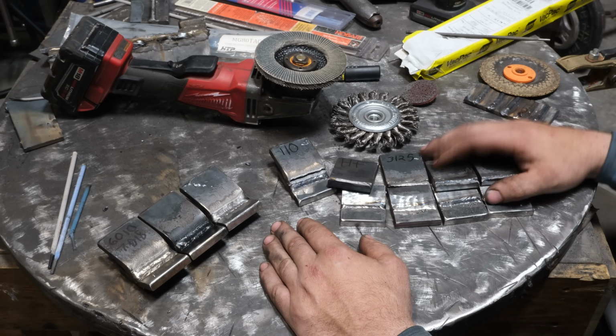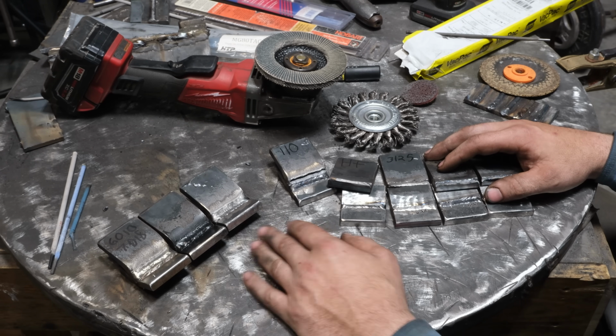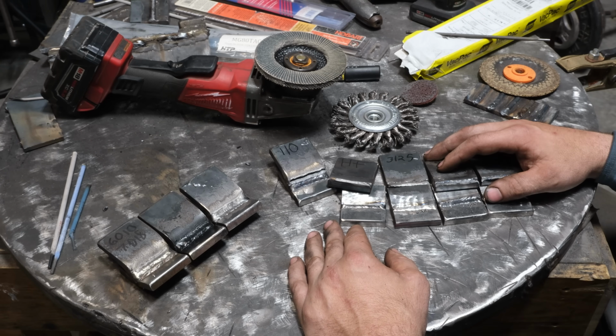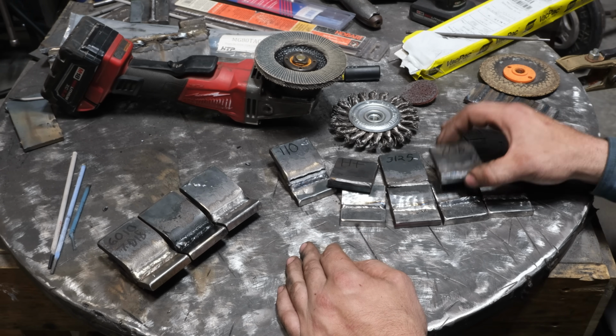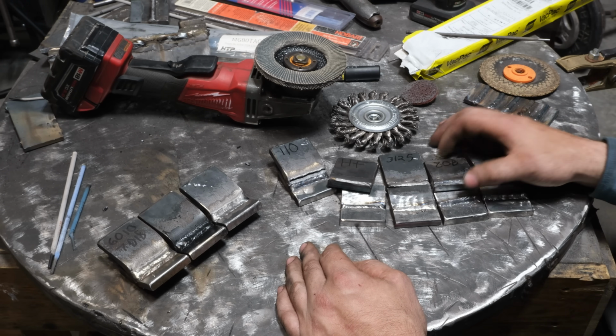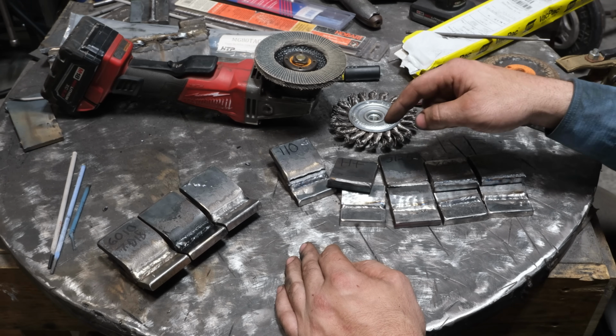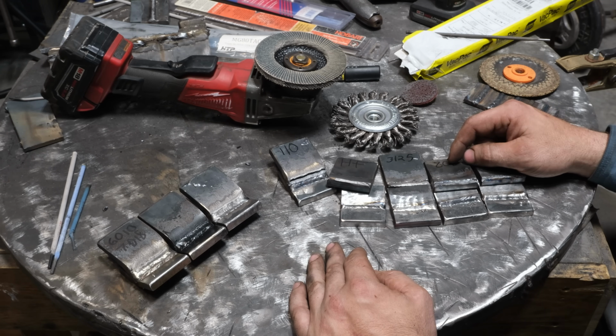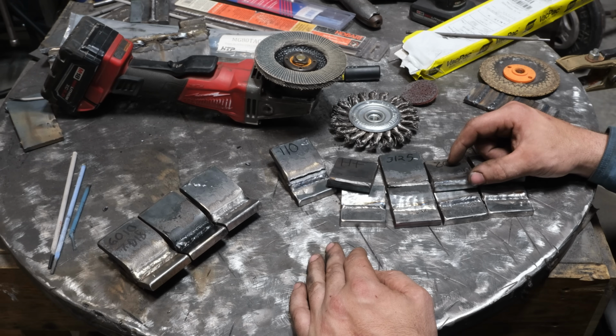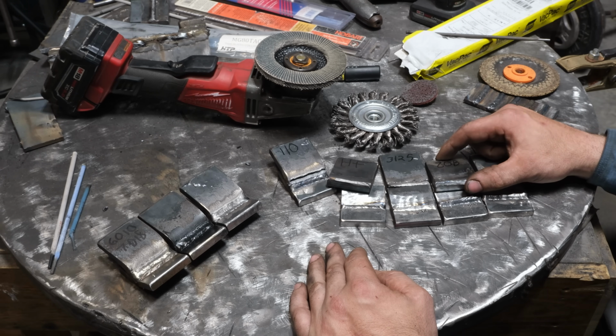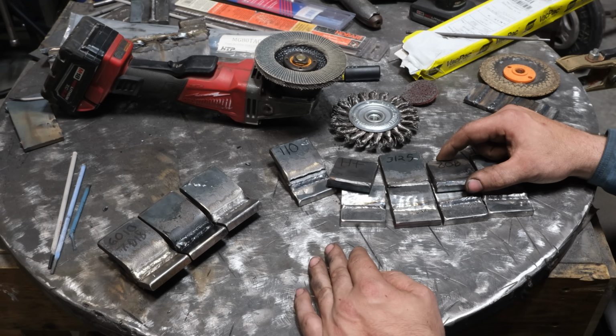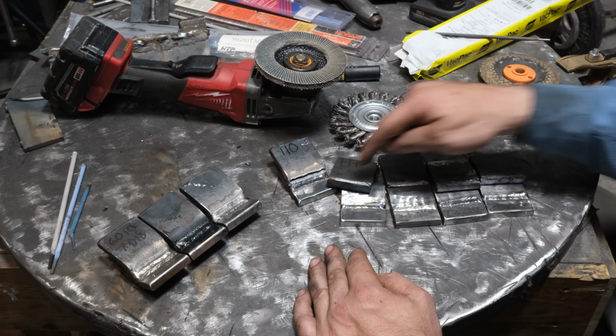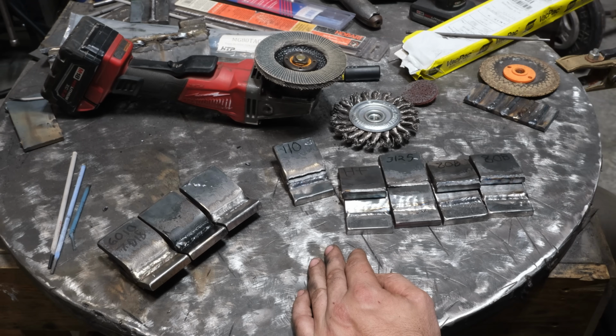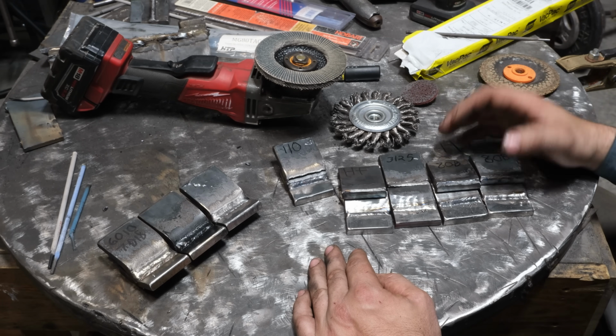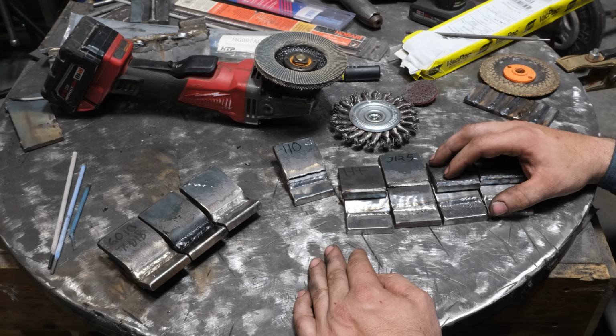Not to mention, if you weld on high carbon steel with a 70 series filler, it's going to become very brittle and it's going to perform more like this blue rod 80 series, or in a worst case, it might even perform like hard face. And I've seen it before when guys weld trusses on rear axle housings and they do it with MIG, and you hit a rock and it busts straight off the casting, just like this did. So it's all things to consider, and it really comes down to at least having an idea of what you're welding on.